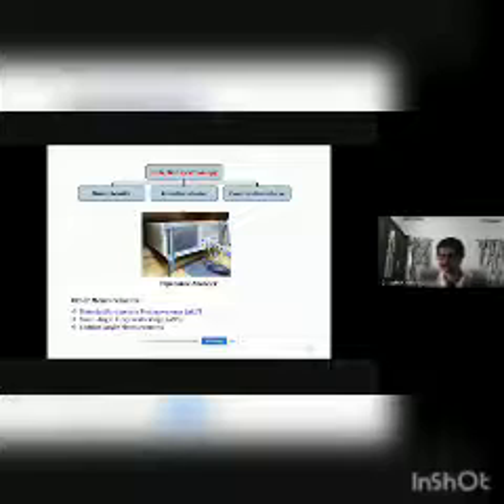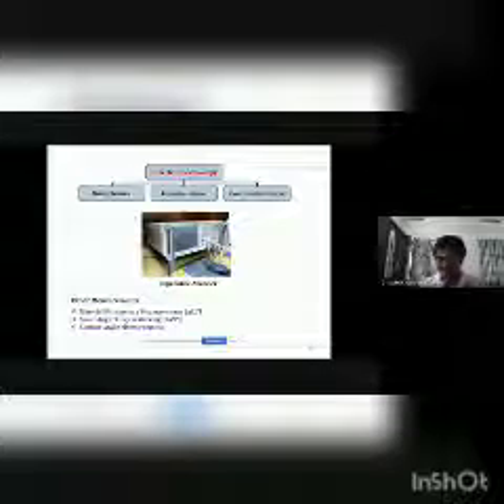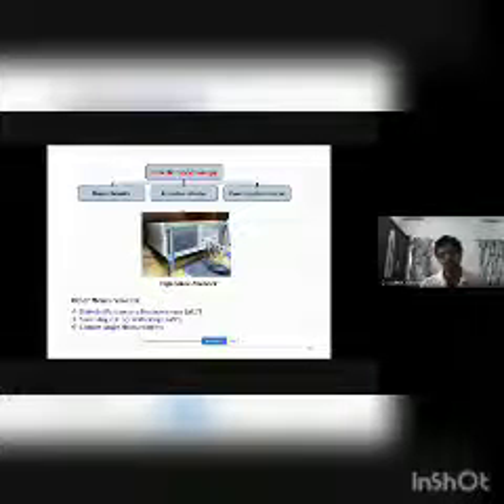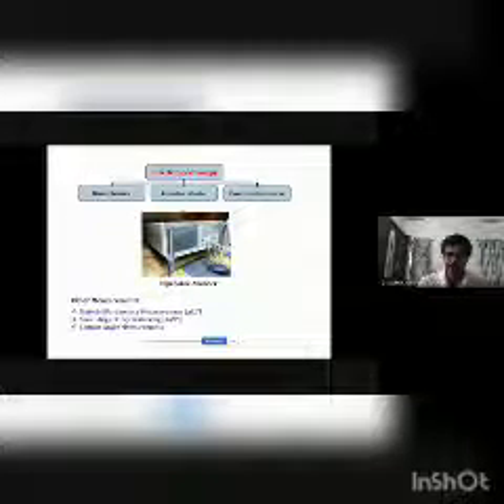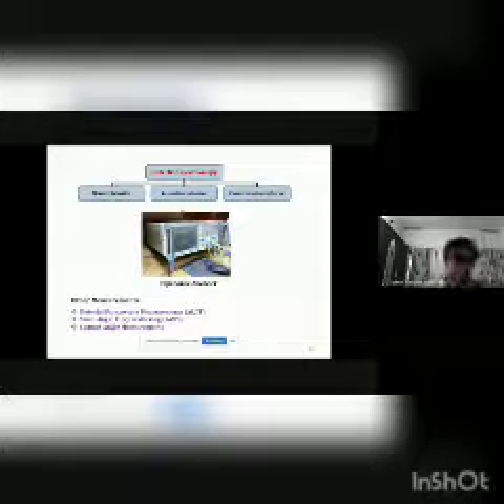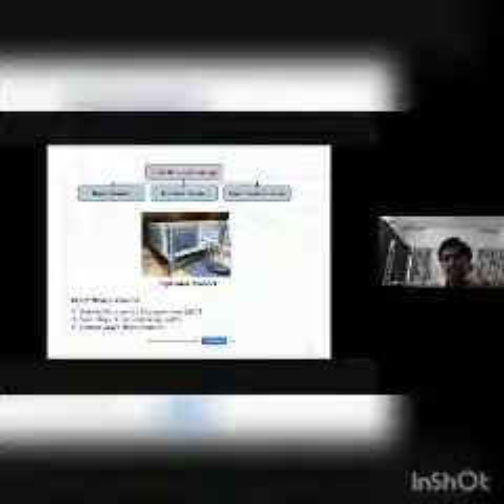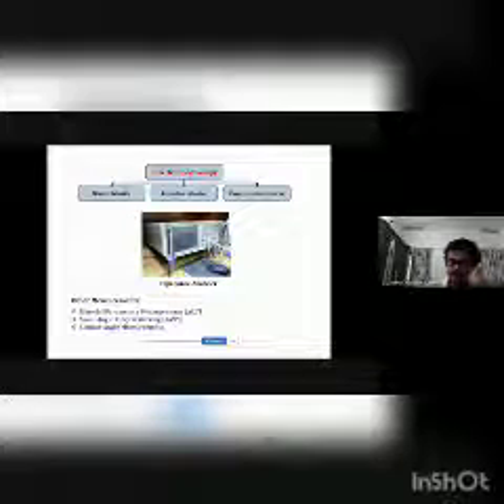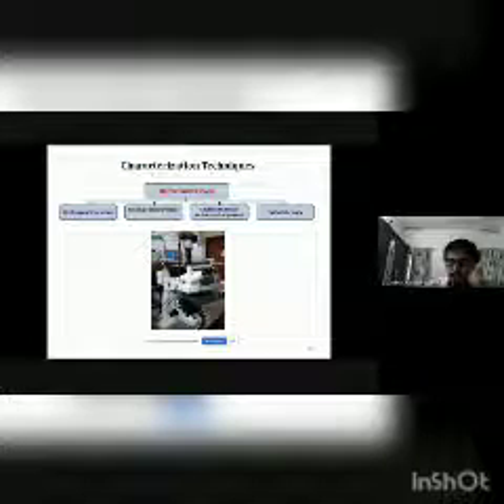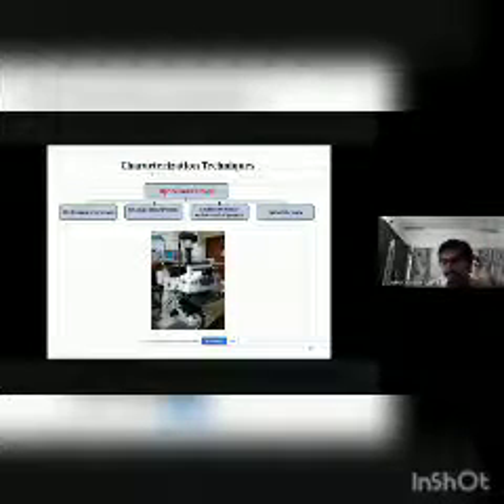In powder XRD, you will be getting an intensity versus angle graph. Here, the distribution of intensities can be mapped in 2D and 3D in small angle X-ray scattering. Moreover, we are using very small angles, varying from some 2 to 3 degrees to approximately up to 30 degrees in SAXS. Then coming to contact angle measurements, we have used different types of contact angle measuring equipment for finding the surface energy of different molecules and also different films and substrates. So basically, if you have a dielectric spectroscope and an optical microscope, you can do the characterization of electro-optical devices based on liquid crystals.